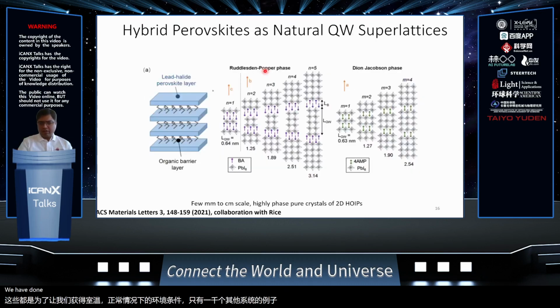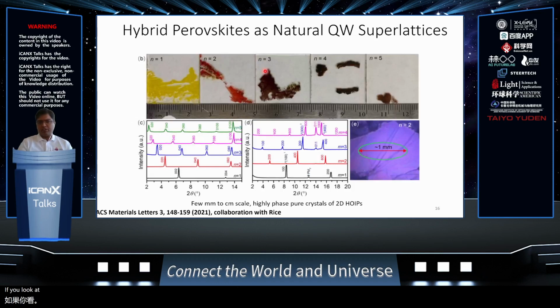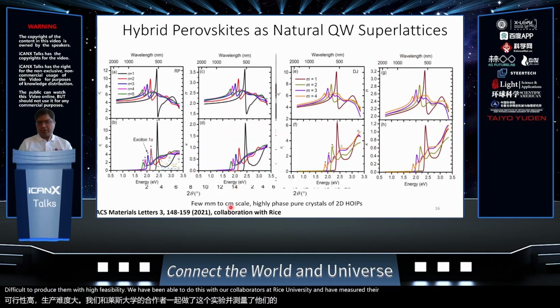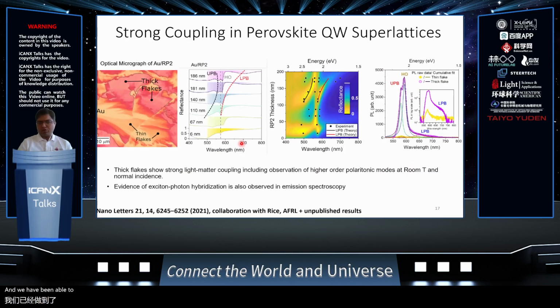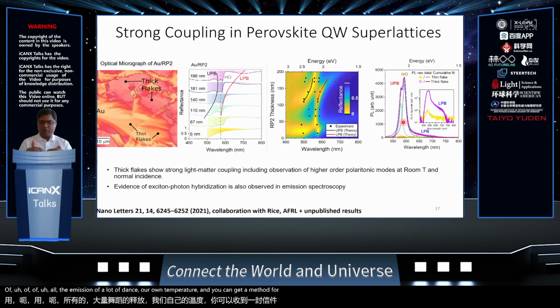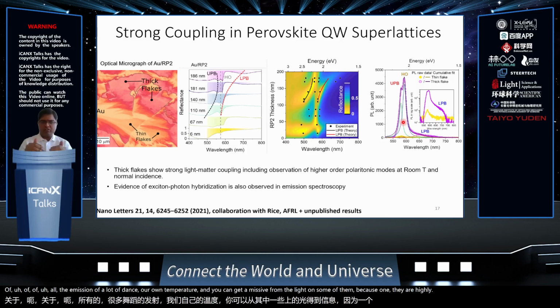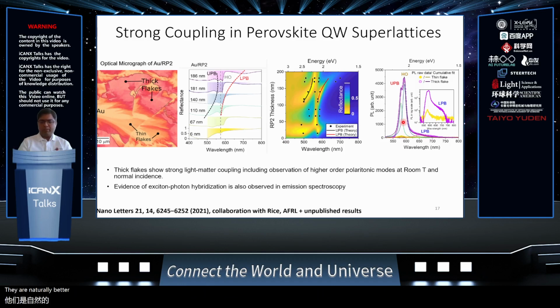We have done similar things with naturally occurring quantum wells. These are the famous halide perovskite materials. If you look at halide perovskite materials, it's difficult to produce them with high phase purity. We have been able to do this with our collaborators at Rice University and have measured their optical dielectric function, which are again very strongly excitonic. And we have been able to also show very strong light-matter coupling in them, including emission of polaritons at room temperature. And you can get emissive polaritons from them because one, they are highly emissive, but two, they are naturally direct band gap at room temperature.